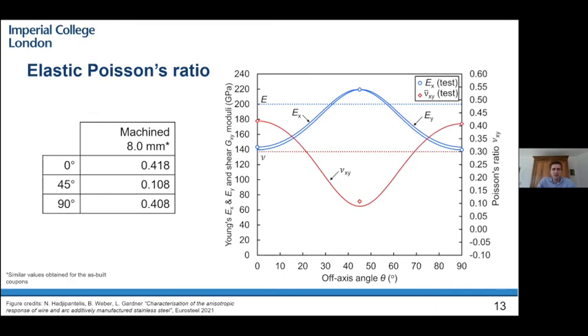However, it needs to be stated here that the Poisson's ratio model is only fitted to the 0 and the 90-degree directions. Thus, the 45-degree direction is not fitting to this model, but it lays very close on the line, which further validates that our orthotropic material model is correct. As an indication, we also investigate how the shear modulus would behave, and you can also clearly see that shear modulus is varying by quite a lot over the different off-axis loading angles.